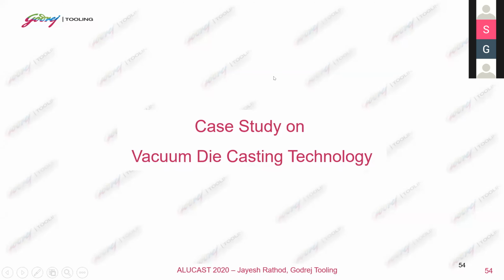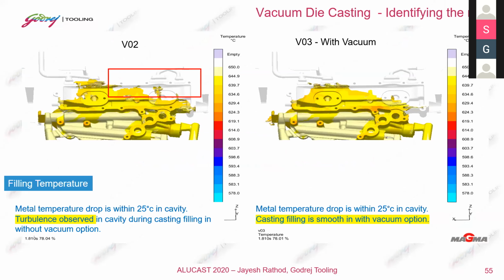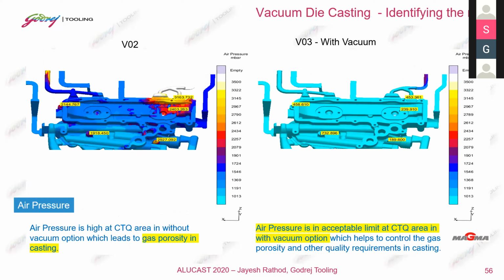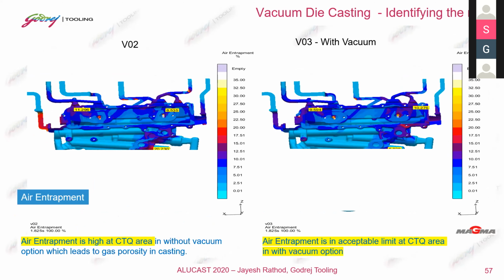So I will just take you through what we did during the development phase. On filling temperature, if we don't consider vacuum in the simulation study, turbulence was seen, and if we apply vacuum, then casting filling was smooth. The second criterion was about air pressure. We could see a lot of gas porosity in the casting, whereas with vacuum, air pressure is within the acceptable limit at CTQ areas. Air entrapment was also very high without vacuum, and with vacuum, it was within the acceptable limit.